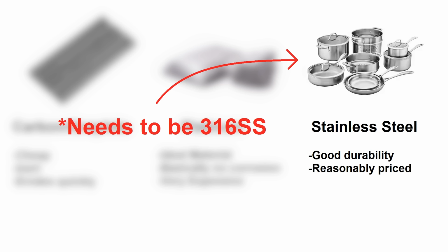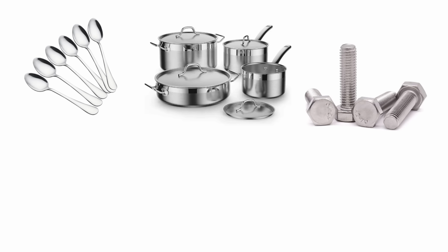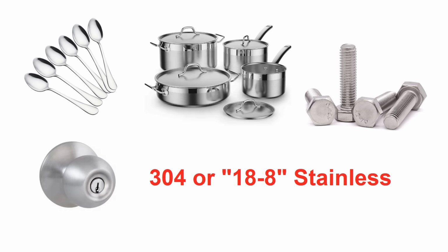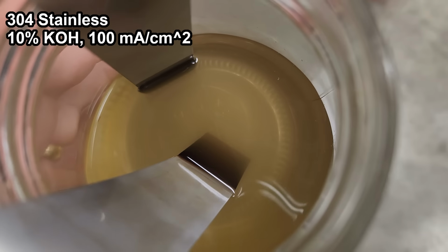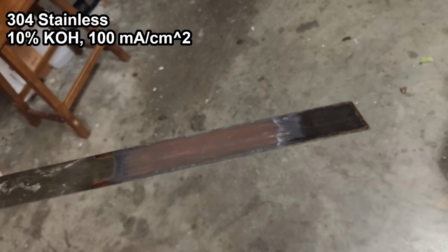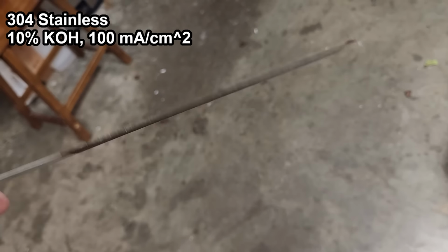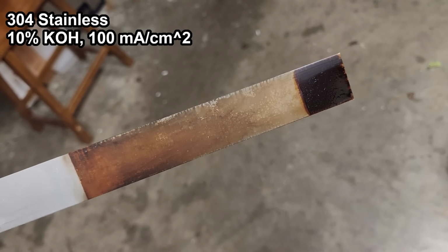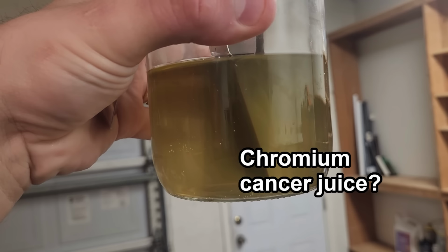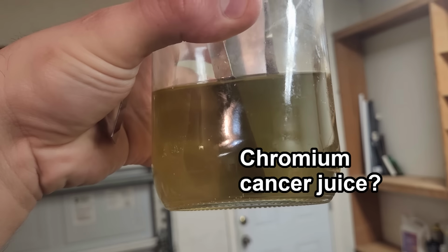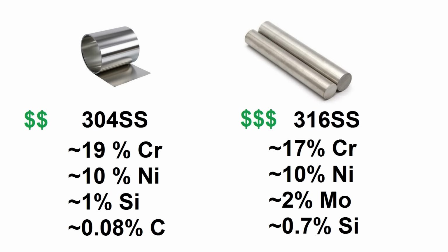Specifically, you need the 316 alloy of stainless steel, which is not the stuff you typically get at the store. The most common stainless alloy is something called 18-8 or 304, which may be fine for doorknobs on your house or on the trim of your car, but won't hold up very long in the alkaline electrolysis environment. Here's an example of what happens to 304 stainless after just a few hours of electrolysis in a 10% potassium hydroxide solution with around 100 milliamps per square centimeter. The plates are pretty messed up and there's some sort of cancerous chromium goo left behind that I really don't want to touch. So yeah, definitely use 316 stainless. It costs more, but it actually stands up to chemical attack.